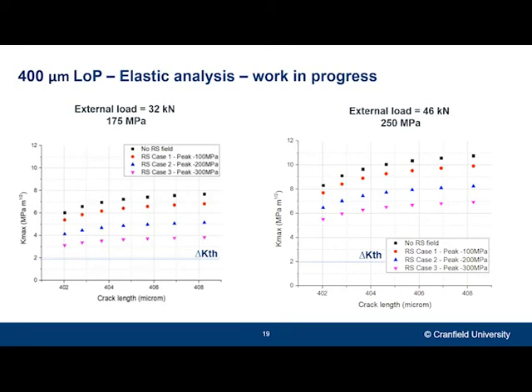However, you can see that for these particular two cases, the delta K is still much higher than the delta K threshold, which is around 2 for this alloy, which basically means that the cracks are still likely to initiate and propagate for these two load cases under those specific stress fields. So basically, once this model is finished, I'll be able to understand what residual stress fields I should try to achieve with the peening treatment in real life in order to get the most benefits and life improvement for this type of joints with this type of defect.